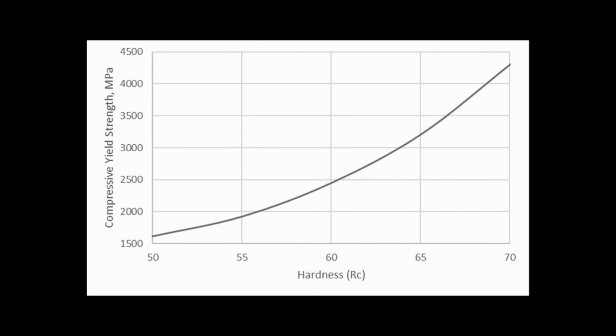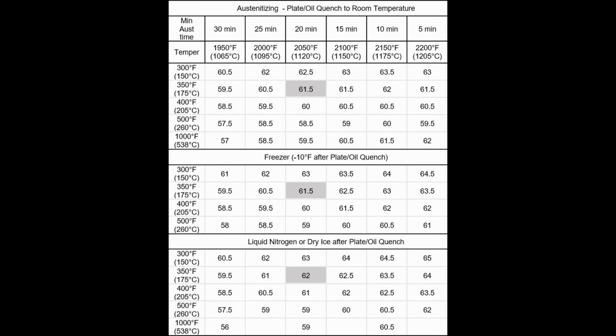In some applications, wear does not come into play that much, and you lose sharpness primarily to other mechanisms such as deformation. So the actual strength of the material may matter more than its wear resistance. MagnaCut can be heat treated to 64 or even 65 Rockwell C when heat treated carefully along with cryogenic processing. So its upper limit for hardness is relatively high. That doesn't necessarily mean that we want to use it at that hardness, but it has that capability.